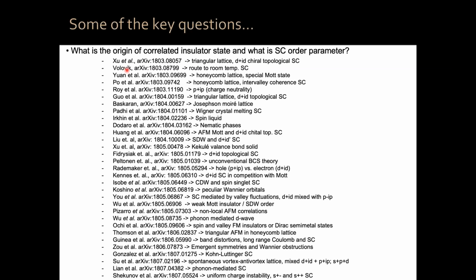Now, Volovik said, this is too many reports for it to be really not true. I tell you what's going on. All of these experiments have been done using graphite which was turbostratic graphite, graphite where there are small misorientations between the graphene planes. If you have these small misorientations between the graphene planes, then you are going to have flat bands and strong coupling superconductivity with very high TC.